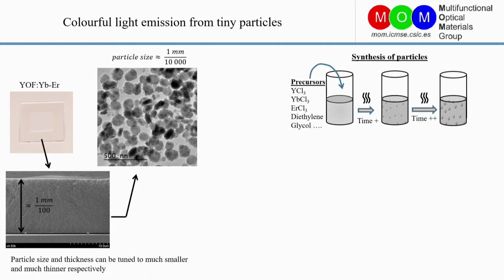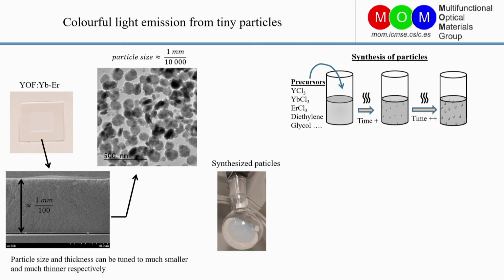The synthesis of particles is very simple. We put precursors in a tube and heat them. After some time, crystals are formed. And when we continue heating the solution for longer, they grow and form particles. Here I show you how the particles look after the synthesis.